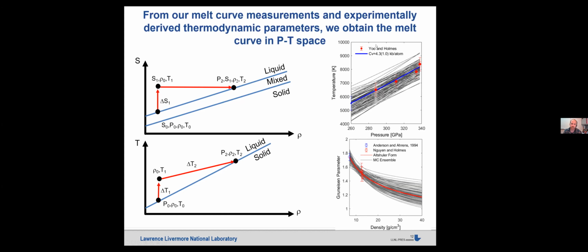So for that, we went back to the Yoo and Holmes data from the 1990s for shock temperature measurements. And actually this data was sort of discounted because the lower pressure data in the solid phase and within the mixed phase region didn't look reasonable. However, I would say that most shock temperature data in the solid phase or in the mixed phase region is difficult to understand because you're releasing through the mixed phase. How do you understand the thermal diffusivities and the reflectivities? But once you get into the liquid phase, those are again more easy to interpret.